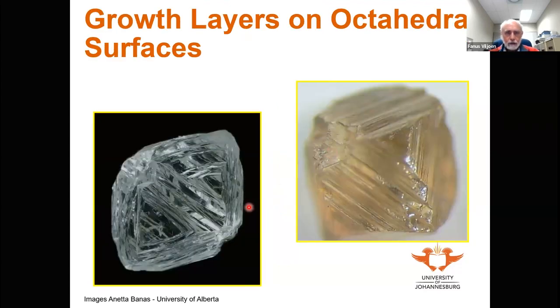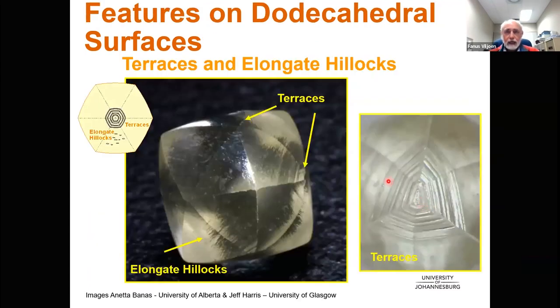Still on the subject of octahedral diamonds in the octahedral crystallographic direction, in this case, the growth layers are picked out by the resorption. You can clearly see the individual growth layers, which are now exposed because of the resorption, and the same type of thing there. And then in the case of highly resorbed dodecahedral diamonds, you very typically see things like elongated hillocks, as well as terraces over here. And a nice example there of terracing.